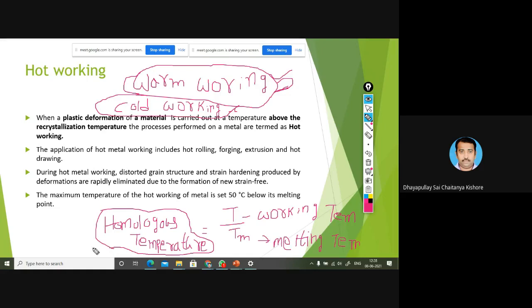Based on this T by Tm ratio, if the value is less than 0.3, then the process we have to perform is cold working. So if T is the working temperature and Tm is the melting temperature, and the T by Tm value is less than 0.3, then we have to perform a cold working type of process.